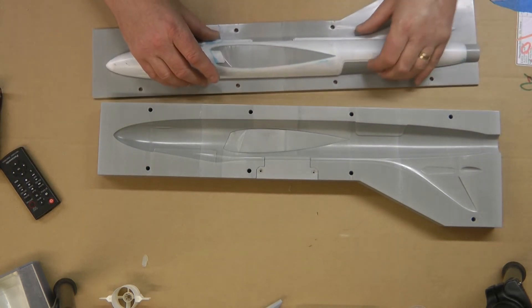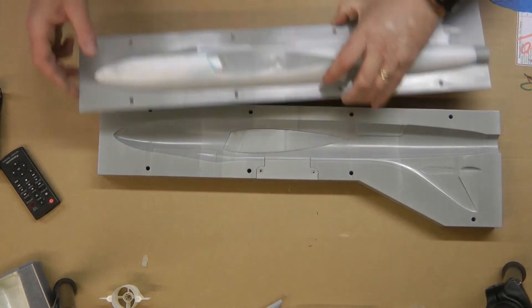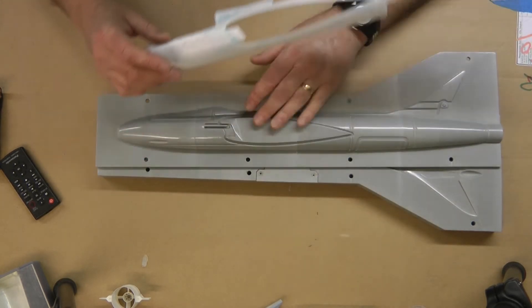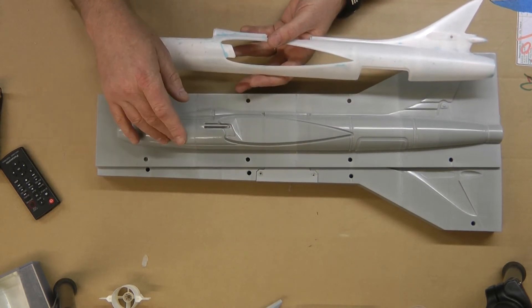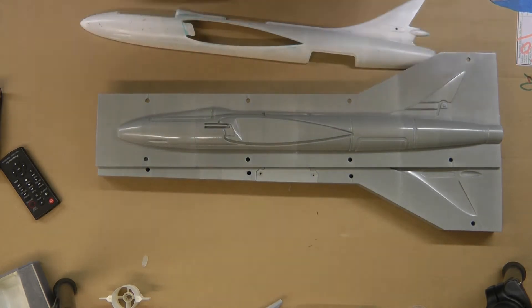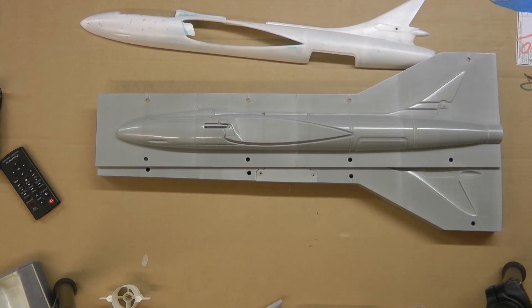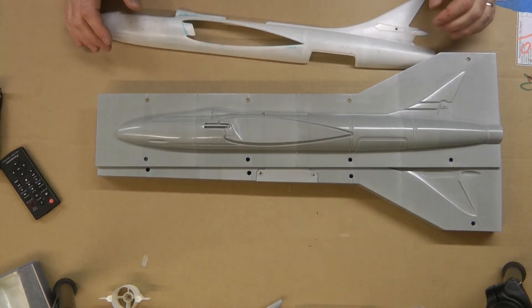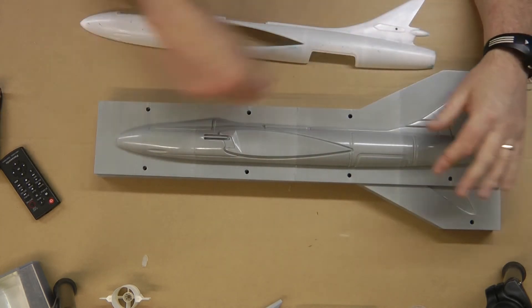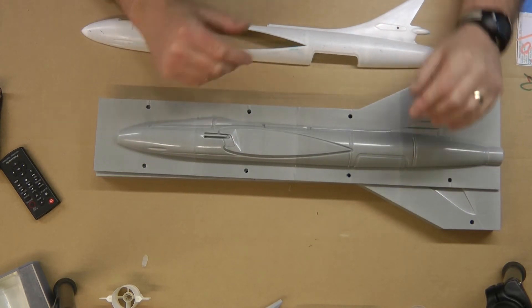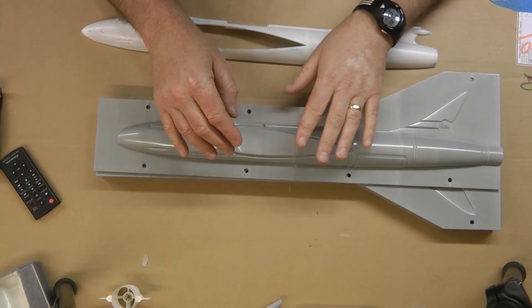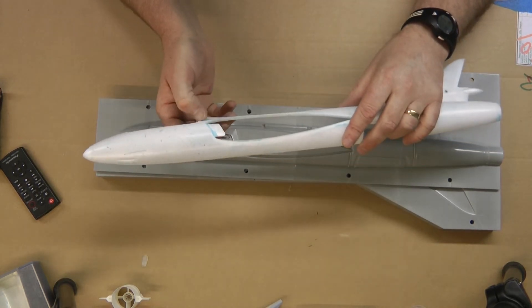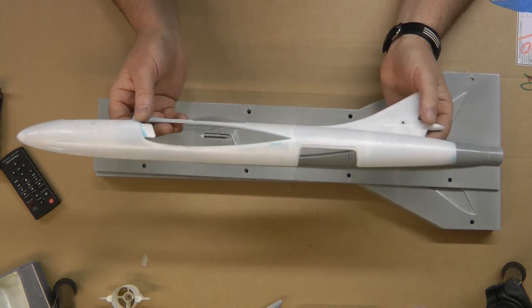Okay, so the pass cut, the actual part cast really, really well. The only sort of problem, you know, you call it a problem, is that some of the PVA must have lifted off the surface. Cause I remember I'd had, I'd polished the wax like a beeswax on here and then I put another, this waxy, a few five seconds. So I'll just get the tin. No, it's not here. It's all down the house. I think it's Ease Release. Something like Ease Release, and there's a number on it. And it's, you paint it on, it's a very, very waxy finish. And I think what happened is it's sort of working too well. And I think the PVA sort of lifted slightly when I was putting everything together off the surface. And then the actual foam actually got underneath it. So this is sort of underneath the layer, as it were, and won't wash off like all the rest washed off really, really easily. Hasn't affected the surface quality at all. Smooth, still smooth.